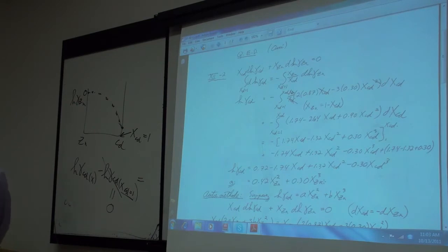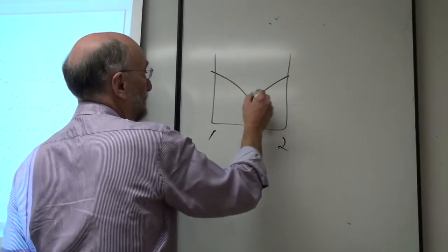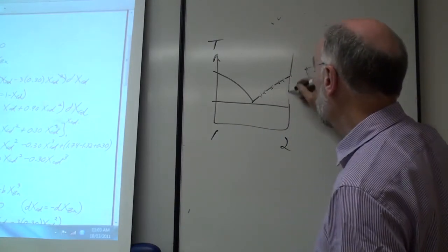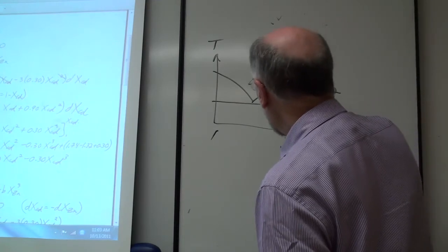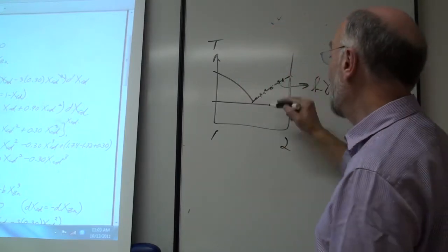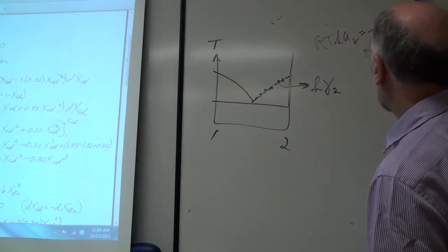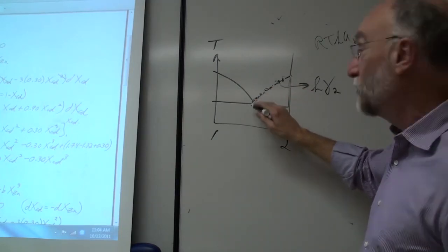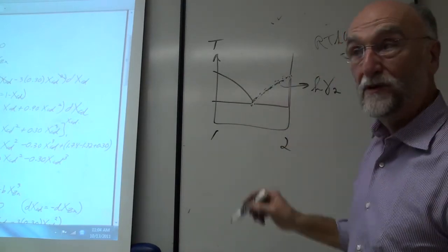Okay, remember this can only work at constant temperature and pressure. One mistake people make, we talked the other day: say I have a phase diagram, temperature versus composition, and over here along this liquidus, if you know that there's no solid solubility and you know the heat of fusion, you can obtain log gamma 2. Log gamma 2 can be measured from analyzing the phase diagram. RT log activity of 2 is minus the heat of fusion of 2 times one minus T over T fusion. You can get log gamma 2 along the liquidus. You say, okay, I got log gamma 2 along the liquidus, I can now integrate my Gibbs-Duhem equation to get log gamma 1. No, you can't, because this is not isothermal. It's got to be isothermal before you can integrate it.